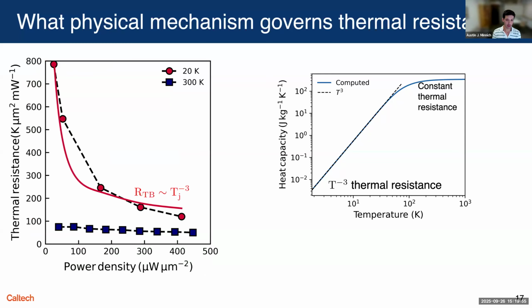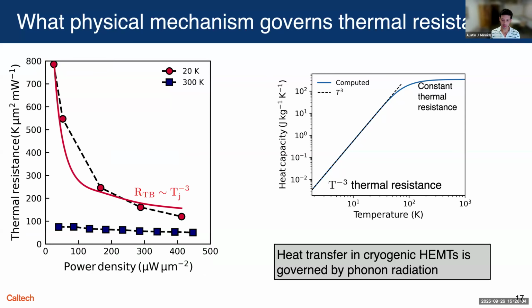That means that the thermal resistance increases very rapidly with decreasing temperature. So if you make a little model just based on that, it really explains the 20 Kelvin data quite well. And so this is compatible with the statement that heat transfer in cryogenic HEMTs occurs not by heat diffusion, but rather by phonon radiation.